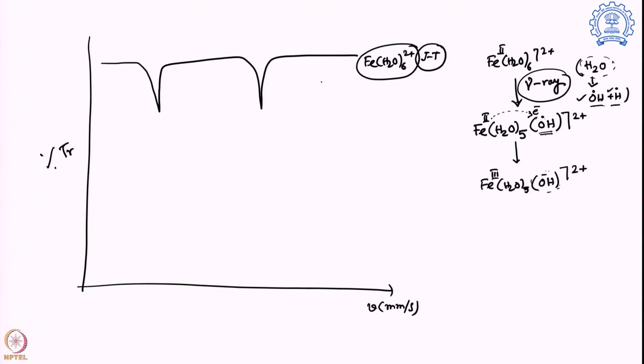So when we begin at 0 minute, this is the spectra we are seeing. No other thing, only iron H2O 6, widely split quadrupolar splitting due to the Jahn-Teller distortion, which actually creates an asymmetry not only from the lattice state but also from the valence state. But what happens when we hydrolyze it?